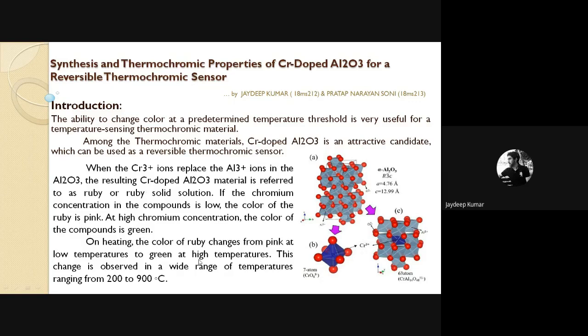If we study this briefly with the ligand field theory, here what happens at low temperature: the chromium ion is a bit bigger than the aluminum ion. In the stable state of alumina at low temperature, this chromium ion is a bit bigger than aluminum. So when it is doped inside, it feels suffocated, like it is squeezed inside the octahedral cage of oxide ions.